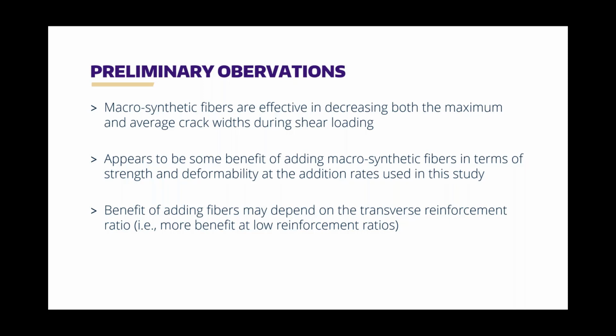There appears to be some benefit of adding macrosynthetic fibers in terms of strength and deformability at the addition rates used in the study. And again, these were pretty low addition rates. 0.52% is not very high in comparison to some of the other tests that have been done up at 1 and 2%. And we're still digging into that, and we're hoping to be able to do some statistical analysis to show whether or not that's significant.